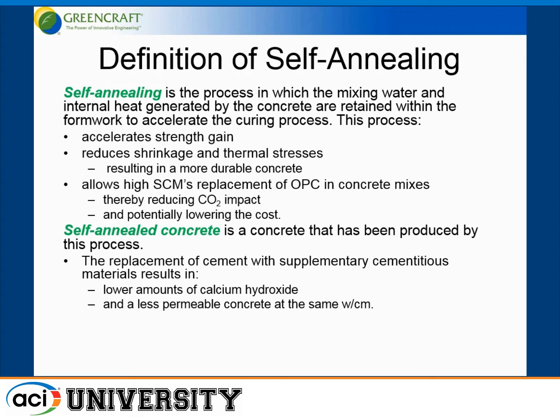This is a new concept that we have struggled with how to define what we're about to show you. Self-annealing is the process in which the mixing water and the internal heat generated by the concrete, the cement hydration, are retained within the formwork to accelerate the curing process. This process accelerates strength gain, reduces shrinkage and thermal stresses, which results in a more durable concrete. And then it allows high supplementary cementitious material replacement of ordinary Portland cement in concrete mixes, which will help reduce the CO2 impact, potentially lowering the cost.